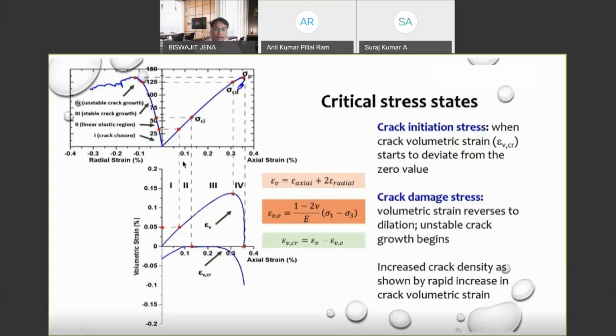So unlike conventional concrete where you have only the peak strength or peak stress, you actually need these two stress states because you are designing this material to carry extremely high loads and be very durable, and crack initiation is not what you want at very early ages. So the crack damage state, where you start to have dilation, is normally the end of the load carrying capacity. So again in sigma CD, 125 megapascal is pretty much what you can theoretically use for design, because beyond that what we are seeing are the effects of loading and a rapid increase in volumetric strain, which is a loading effect. So you do not want to consider that. So crack initiation and crack damage stress are about 25% lower than peak stress. So two different critical stress states are here.